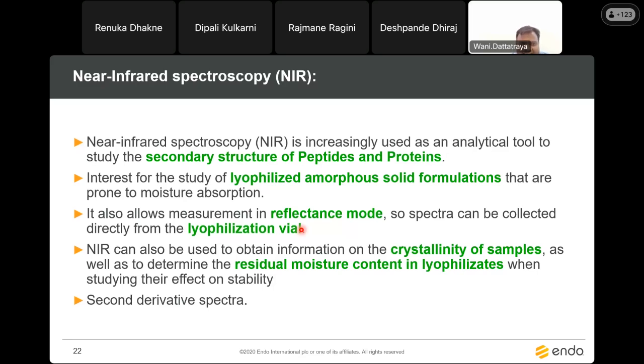An advantage of near infrared spectroscopy over FTIR is that we can use it in reflectance mode, whereas FTIR can use only transmittance mode. So you can directly analyze your lyophilized vials, and you can use that sample for different analysis techniques, so there is no sample disturbance. With this technique, we can study secondary structure and crystallinity of the sample, as well as lyophilization cycle optimization, and we can determine the water content.